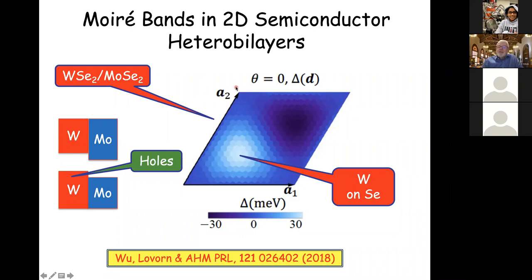The Moiré pattern in typical experiments has a lattice constant of around 10 nanometers. So in fact, you can think of these as artificial crystals with giant atoms that have a size of about 10 nanometers and are separated by a distance of around 10 nanometers.